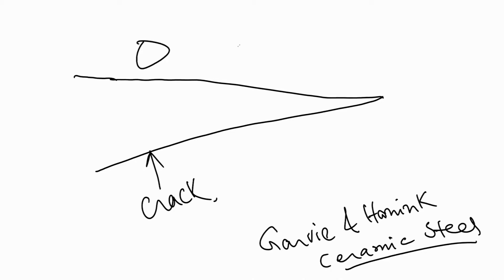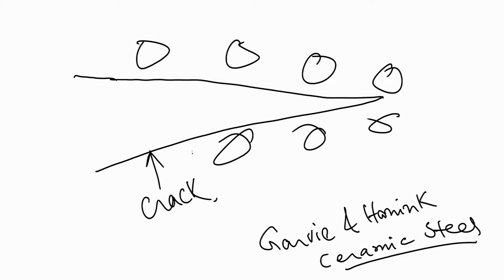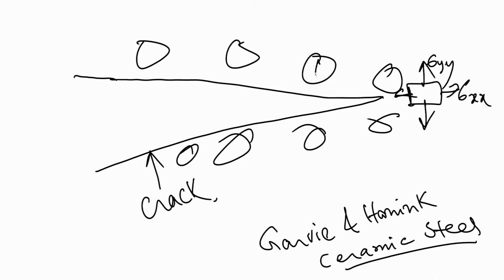So, around the crack face, if tetragonal zirconia is retained in the phase, and then a crack tip has a particular stress field, right, in the tensile stress field. Now, in the crack tip stress field, suppose this is sigma xx, this is sigma yy and all. Suppose in the crack tip stress field, this is your T phase, tetragonal zirconia phase. If tetragonal zirconia phase, they transform to monoclinic zirconia.